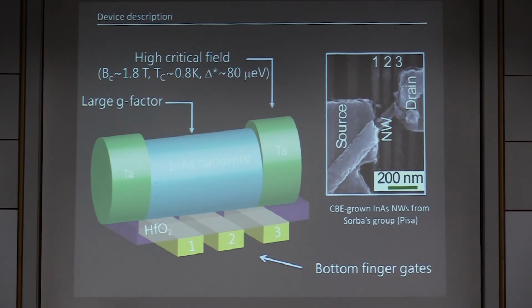Now I'm going to show you an experiment where we look at a quasi-ballistic regime. Again, the channel is quite short, but we add another ingredient, which is the possibility to have multiple gates with which we can tweak the potential in the channel and make it as ideal as possible. That's more or less the underlying idea behind this experiment. You can cure possible inhomogeneities or possible bumps in the potential and have a system that is as ballistic as possible. So there's this additional degree of freedom.